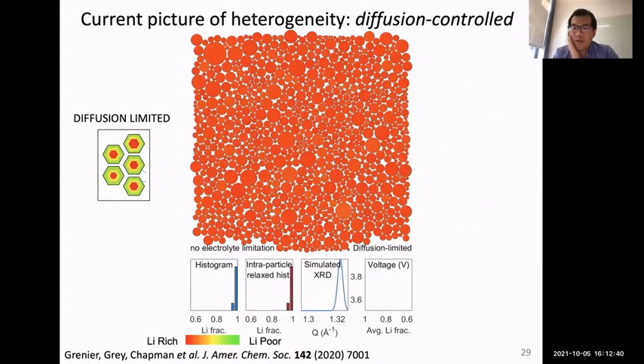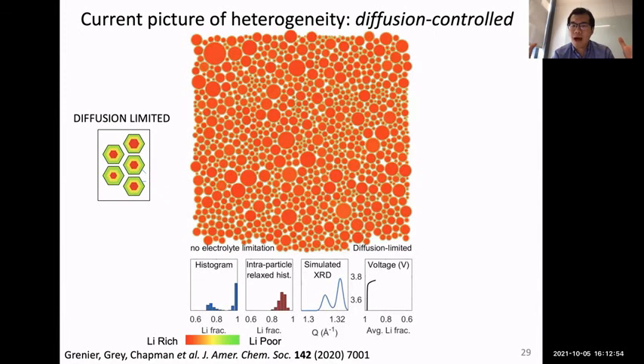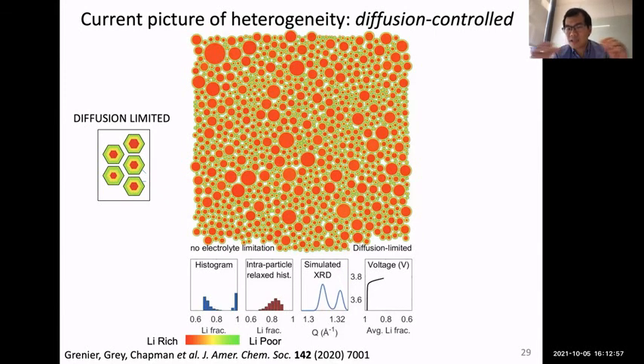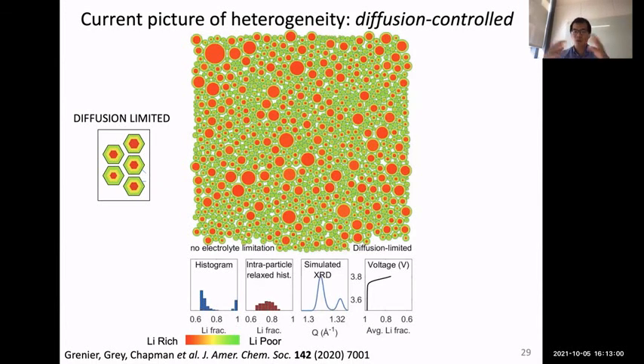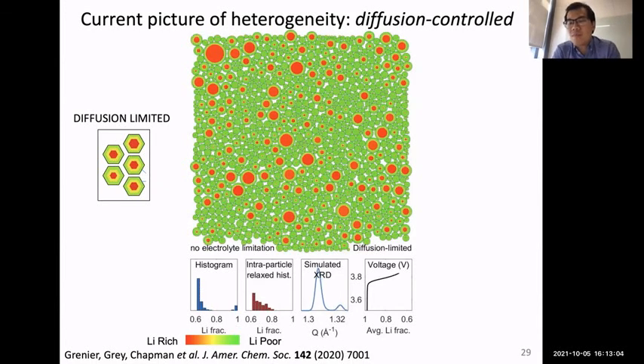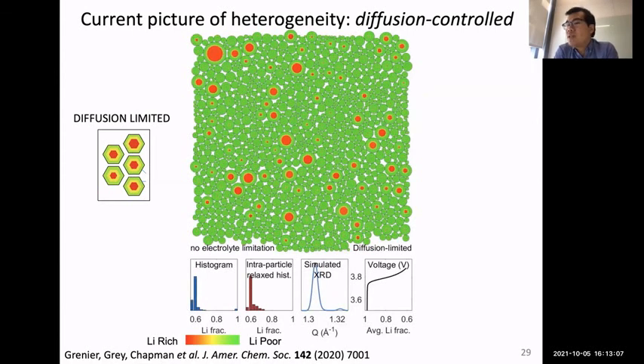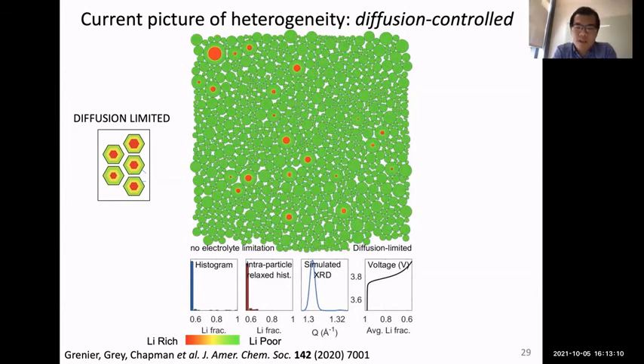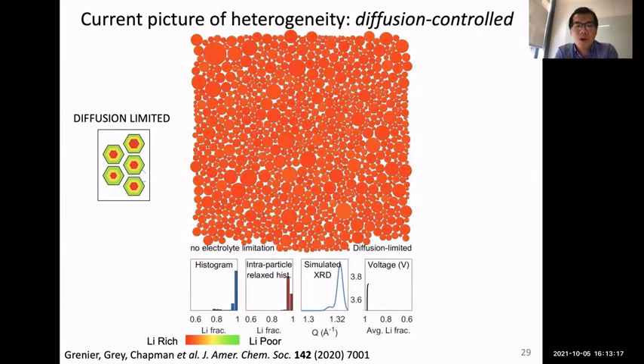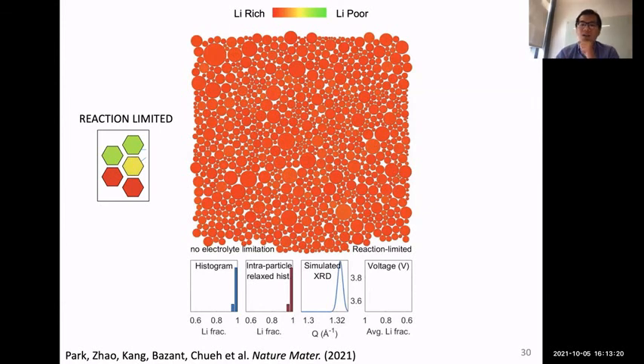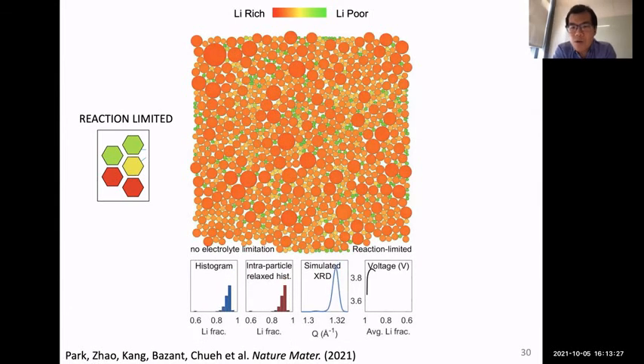So let me show you how we did. Again, I know this is not a battery audience, so I'll just show you schematically what is happening. This is the model that most people think happens in the battery. It's called a transport control model, whereby the insertion and removal of lithium is controlled by diffusion inside the particle. So you see this core-shell behavior. When we ran it through our machine learning model, we found that the experimental data can only be partially explained. So we asked ourselves, what other heterogeneity can be more consistent with the data? We solved this inverse problem. And it turns out that the model that correctly explains all experimental data is this one. This is what's called a reaction limited model, or interface limited model.